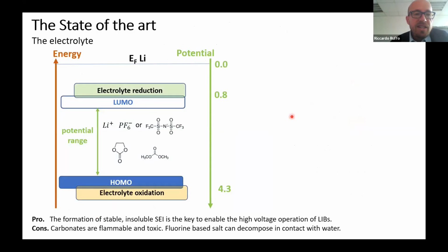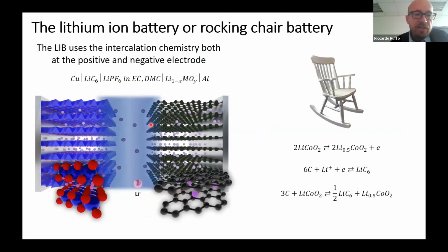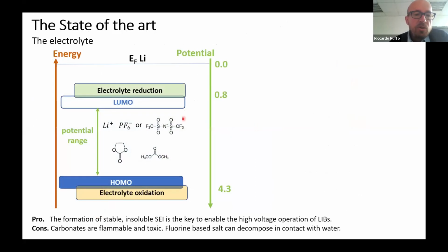So the state of the art, let's start from the electrolyte, which is the heart of the battery, where lithium ions are exchanged between the two electrodes. Lithium-ion batteries cannot work with water because the materials that are produced during the charge are unstable in water. So we need to use a complex combination of solvents like carbonates and lithium salts.